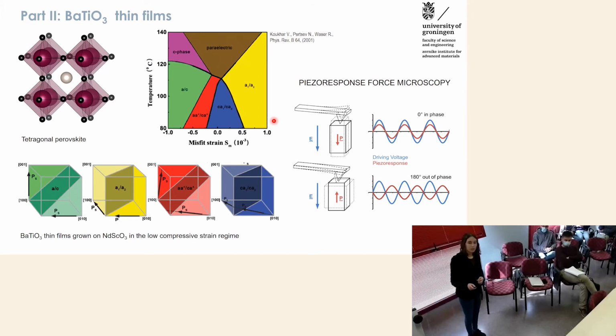And what is interesting is, of course, that because this is ferroelectric and ferroelastic, we can measure and characterize which phase it is in by means of piezo response force microscopy. So what we did with these films is grow a barium titanate on a neodymium scandate substrate, which induces a very low compressive strain. And we can assess the transition between this in-plane and alternating in-plane, out-of-plane phase at a reasonably low temperature. And we follow this phase transition by means of piezo response force microscopy.